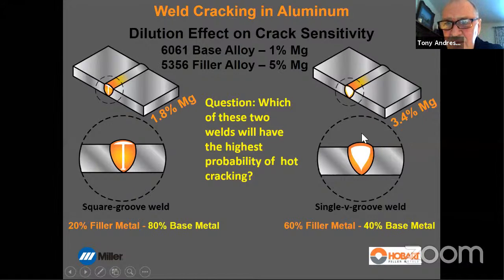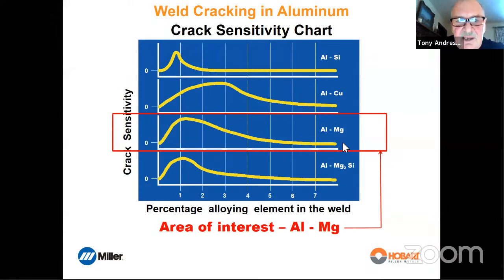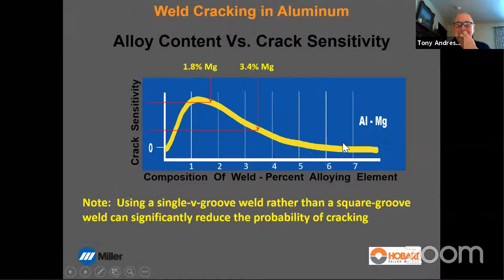Now we put this prep, we change this to 60% filler, so 60% of 5% mag and 40% of 1% mag. We end up with 3.4% magnesium in this weld. So this weld has 1.8% magnesium in aluminum, and this one has 3.4% magnesium in aluminum. Which one's going to be most crack sensitive? 1.8 is almost at the peak crack sensitivity. 3.4 drops the crack sensitivity all the way down here. So the probability of cracking when you use that V-prep is reduced substantially.